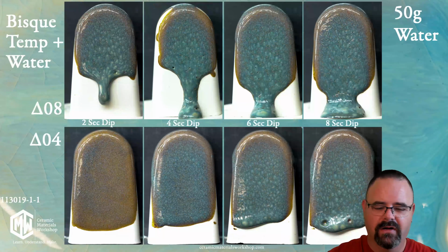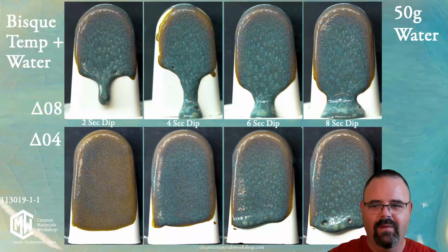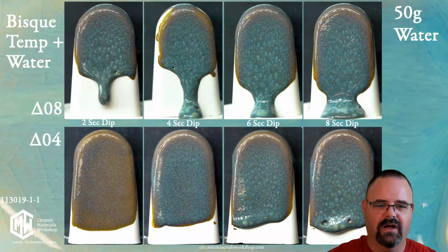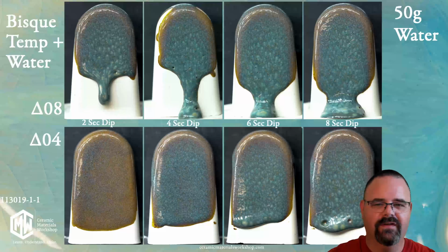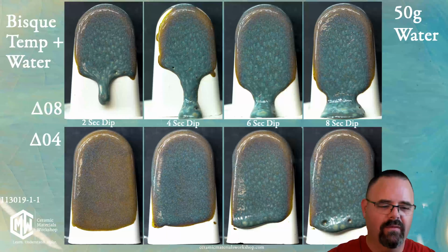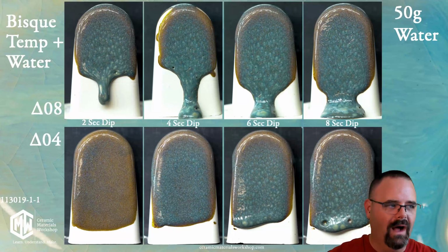You see, here are 8 glazes, except once again, they are all the same glaze. And what we have here, though, are 2 different variations on the glaze. This particular one is the same glaze with 50 grams of water. And what we have is a 2-second dip, a 4-second, 6-second, and 8-second of the same DDM222 glaze. But the difference is that on the top row, the clay was bisqued to cone 08, and on the bottom row, the clay was bisqued to cone 04. Well, isn't that interesting? These are all exactly the same glaze. Why do we have such variation based purely on bisque temperature?